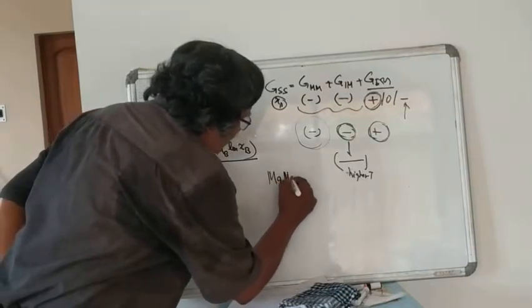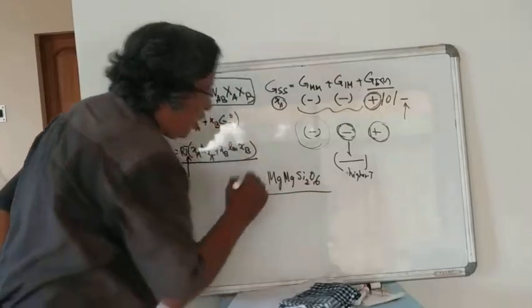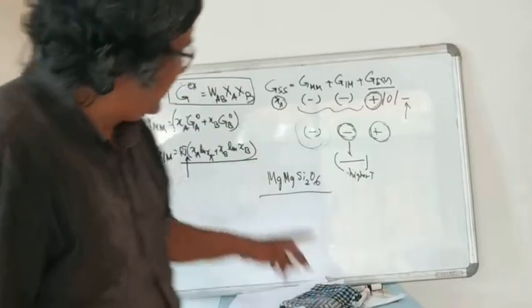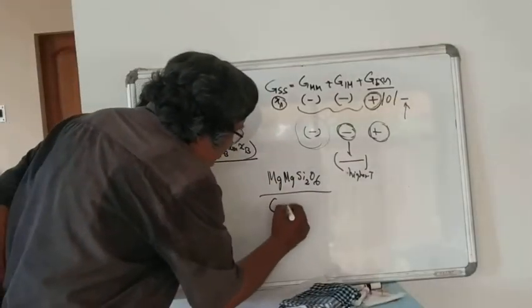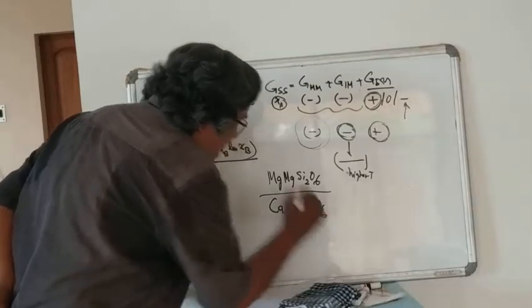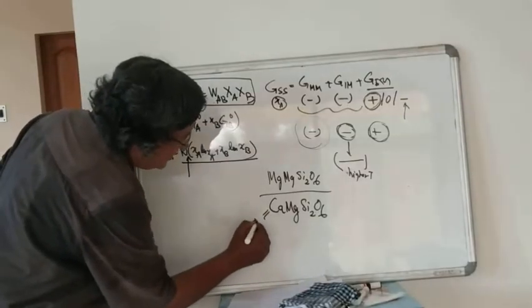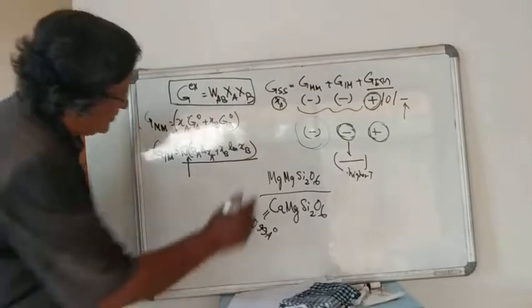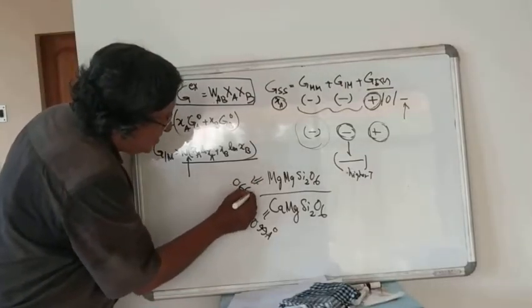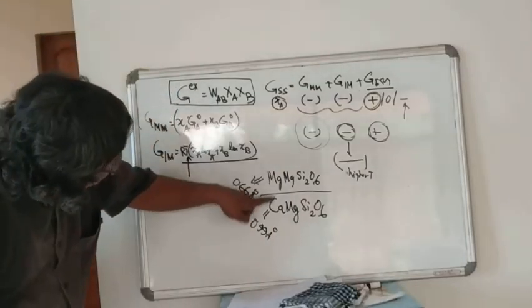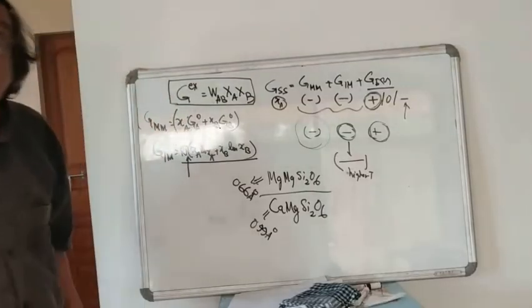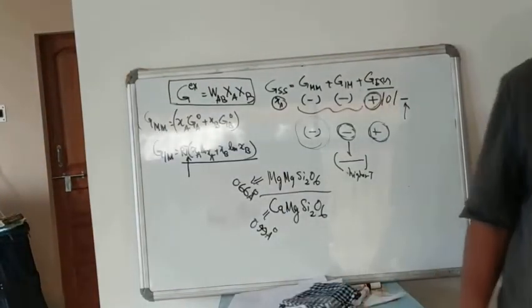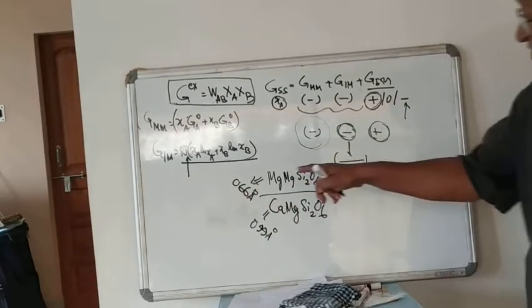Can you give me an example? Say, for example, you know this mineral, I think all of you should know, MgMgSi2O6, this is called orthorhombic pyroxene, or orthopyroxene, its name is enstatite. And say you have CaMgSi2O6. Now what happens? This calcium has an ionic radius of 0.99 angstroms, and this magnesium has an ionic radius of 0.66 angstroms. So these two magnesiums have no problem. Only these two have a problem because the size difference is more than 33%. 0.66 divided by 0.99 is 2/3. That means 1/3 ionic radius less.